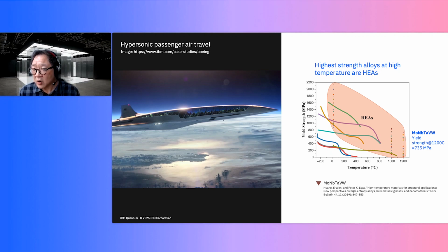Now, one of the challenges with high entropy alloys is they're much more complex than typical alloys. As I said, most alloys used for high temperature structural applications are nickel alloys, so they have one principal component. They may have a lot of dopants, in the 1% to 2% range, but the principal element is nickel. Whereas in these high entropy alloys, you can see the formula for the highest strength alloy at 1,200 degrees C: molybdenum, niobium, tantalum, vanadium, tungsten. So there are 5 principal elements here.